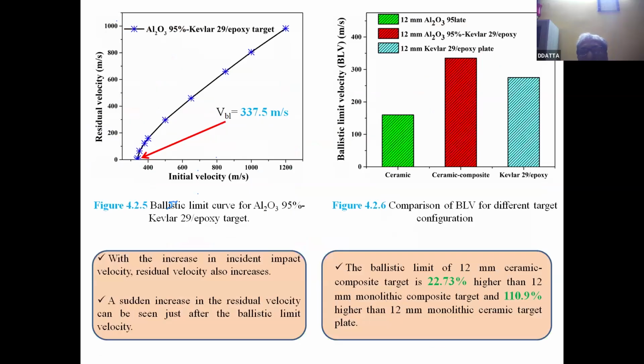There is some comparison. You can see that there are 3 cases, and we have a bar diagram. The green one is 12 millimeter Al2O3 alone. That means the ceramic. If you make a ceramic plate of 12 millimeter thickness and you impact it, the ballistic limit velocity will be around 150 meter per second.